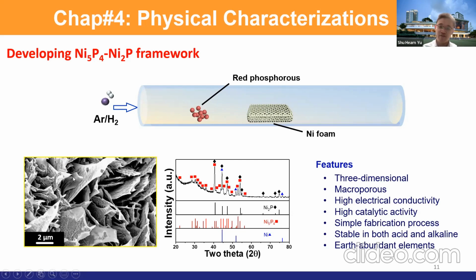At around 800 degrees, I find that these sheet structures will melt and merge with each other. So the surface area is reduced. And that's why I keep it at around 500 degrees C. The features of this nickel phosphide are that it is three-dimensional. Some people like to do two-dimensional electrodes. I find that the surface area is limited and the active sites could be limited. Therefore, I prefer to use nickel foam. And it's macroporous. Macroporous means the electrolyte can go in and out very easily because these are porous structures. So the ions and the electrolyte can be refreshed quickly.